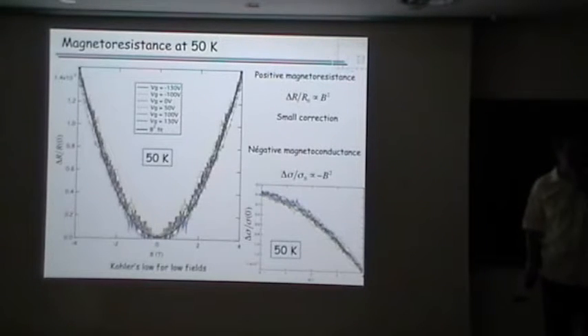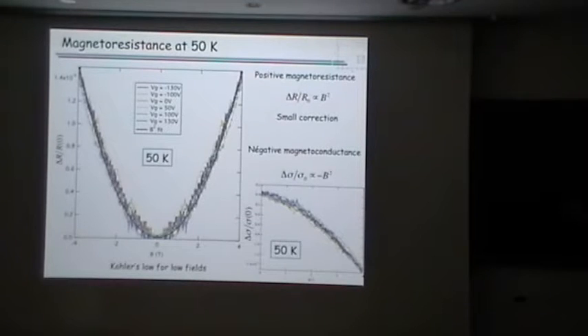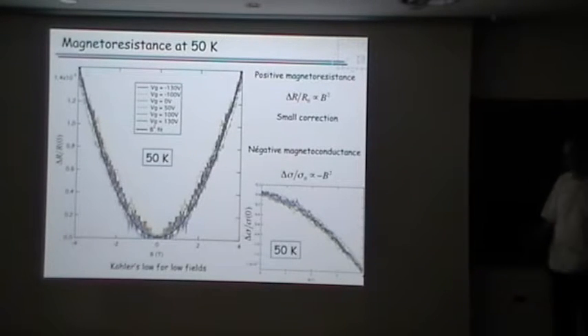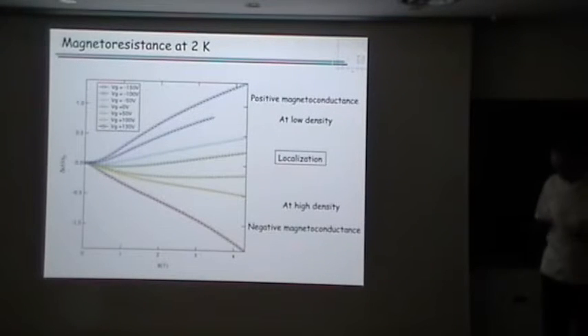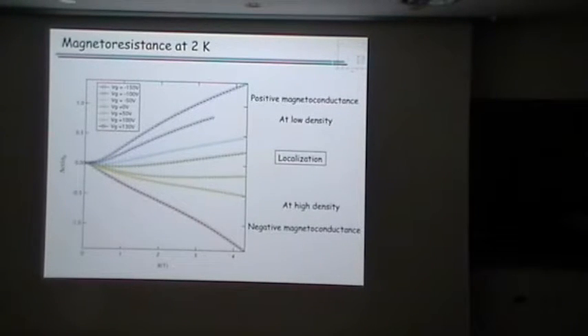Now if we put a magnetic field, first of all at high temperature, whatever the gate voltage, we have a perfect B-square behavior, like the Kohler rule. That means you have a negative magnetoconductance, which is what you expect for a regular system. I chose 50 Kelvin because, as you remember, at about 50 Kelvin the behavior is conventional in the system. Now if you go to low temperature, like this is 2 Kelvin, and this is the variation of the conductance as a function of field up to 4 Teslas, what you see here is that for negative voltage you have a positive magnetoconductance, and for positive voltage you have a negative magnetoconductance.